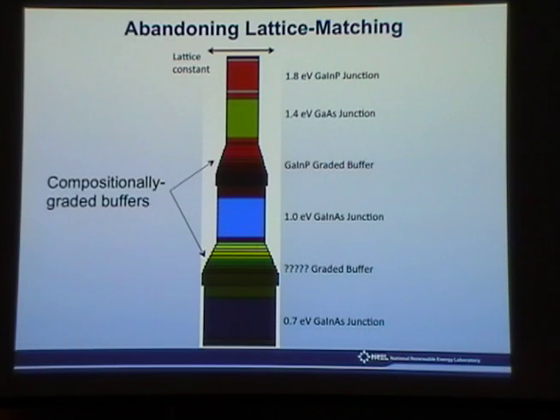Yeah. So I guess following up on that, if that is a lower energy state, why would those not just get bleached and saturated and then be no problem? In other words, with light, why would those trap states not fill up with free charges and then no longer be a problem? They might. Some of them might. They are electrical defects, like other electrical defects, but they probably have a much higher cross section. So you would probably need an enormous amount of light to fill them up effectively.